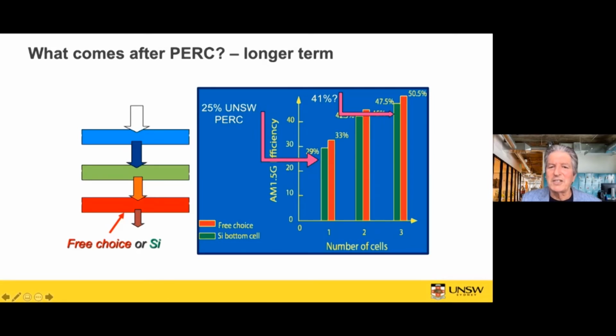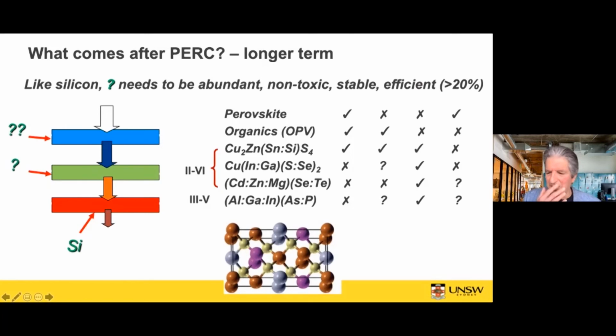For a single junction cell, silicon has a limiting efficiency of 29%. We got to 25% with PERC, and I think we'll see those types of efficiencies in production. The red line just shows what you can do if you had any choice of semiconductor, if you just dumped silicon and could use any other semiconductor with idealized properties. So silicon is a very good choice, as these slides show. But with 2 cells stacked onto silicon, if you can get the same percentage of the available performance, you'd be up over 40% efficiency. So a big jump in efficiency if you can perfect this technology.